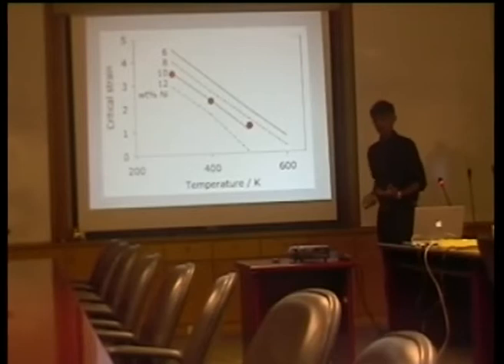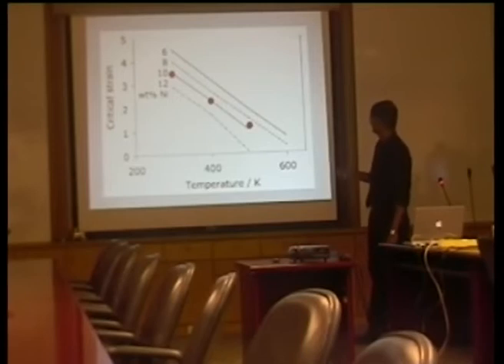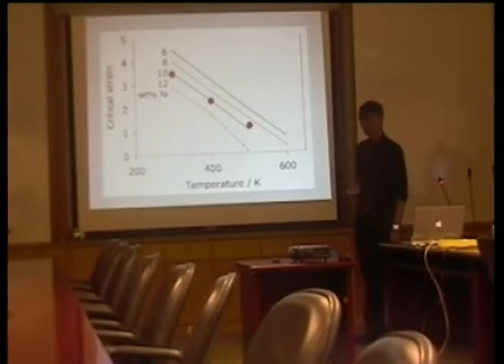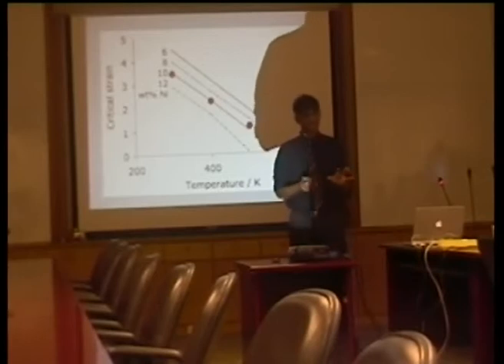And here are the predictions of the strain at which mechanical stabilization will happen. This is for the four different ideal alloys and this is for 316L. And room temperature is around here, and according to this, at room temperature, I should get mechanical stabilization at a strain of about 2 in 316L.